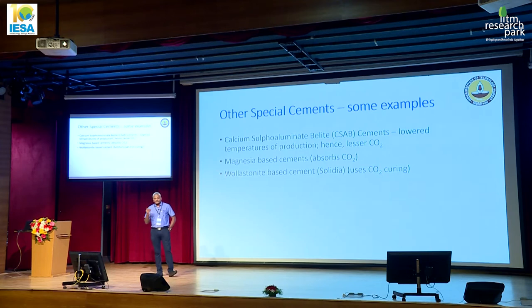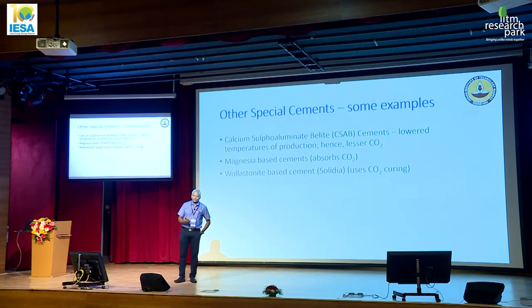So the other special cements that are being talked about a lot in the world: one is calcium sulfoaluminate belite cement. Here, the temperature of production of the cement is lowered. So the amount of energy required to produce the cement also is lesser than ordinary Portland cement. And the overall process evolves much less CO2 because the extent of limestone in the mix is a little bit lesser. Okay? It has problems of stability in the long term. So there are still some challenges with the use of this cement. It has some problems of early strength, which is why in construction projects, which depend extremely on early development of strength, we have a challenge of using these materials.